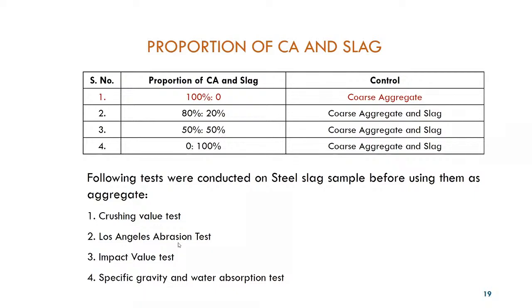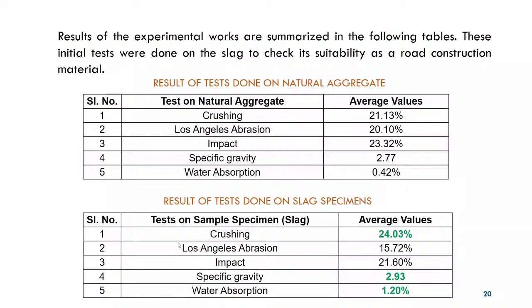Now, before casting the cube, first of all, as I have told you, the slag has to be tested for its appropriateness. For the intended use, if he is proposing to use it as a concrete pavement, it has to prove its appropriateness. So for that, the steel slag should be tested for the similar parameters of the aggregate as well. So the tests done were crushing value, Los Angeles abrasion test, impact value test, you people know better than me all these values, those who are actually specializing in the stream, specific gravity and water absorption.